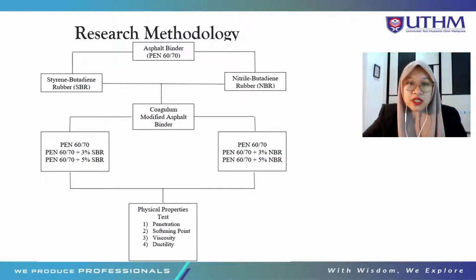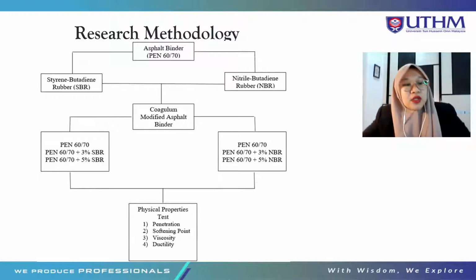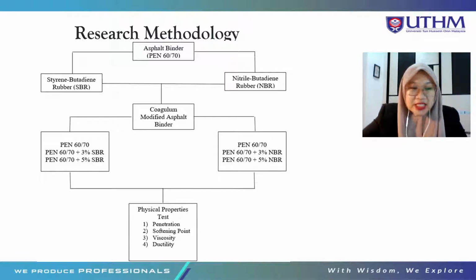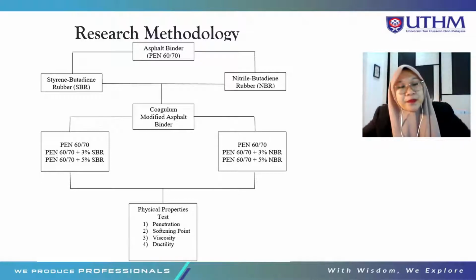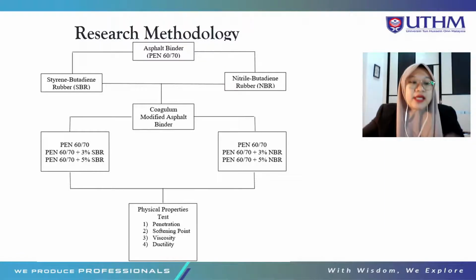This is the research methodology for this study. The 60-70 penetration asphalt binder was blended with SBR and NBR at concentrations of 3% and 5% by weight of asphalt binder. The coagulum modified asphalt binder was prepared using a high shear asphalt binder mixer. About 500 grams of base binder was heated in the oven at 170 degrees Celsius until fluid. Before adding the additive, the asphalt binder was stirred for 5 minutes to obtain uniform temperature distribution, and the coagulum was then added progressively. The mixer speed was maintained at 2000 RPM for 120 minutes, around 2 hours, at 170 degrees Celsius to allow good homogenization.